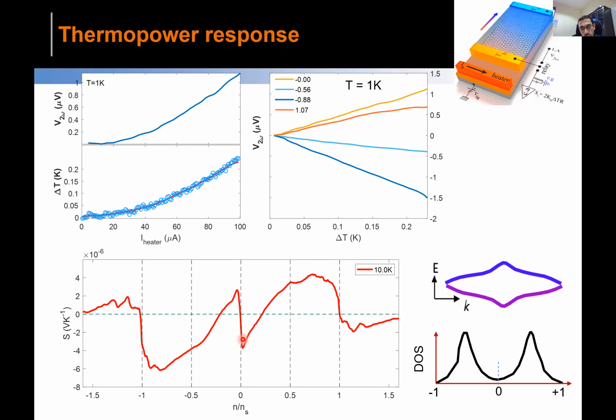You see, this goes down, then it goes up again. And again, there are several sign changes. There is an interesting point. This sign changes from this theory, as I told you, it has to be at the symmetric point. And that symmetric point is 0.5 and minus 0.5 and plus 0.5. That should have been here, but rather we see it somewhere close to 0.3. So that itself is very interesting physics, which I probably don't get time to discuss. But let's see what happened to this thermopower spectrum.